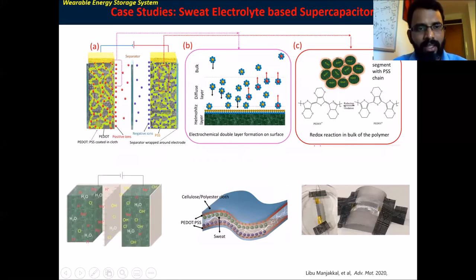And then you can see here such a cloth. Because this PEDOT:PSS is a conjugated polymer, it's a conductive polymer also. Due to the PSS, it's insulative, but we are using a DMSO also to increase the conductivity of the PEDOT:PSS. And then there is a network for ion conduction. And then you can see here such a cloth, two identical cloths bonded together. And again, I used a separator.